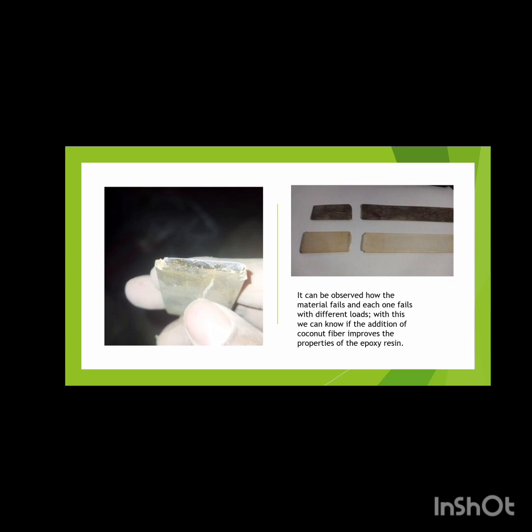After performing the tensile test, it was observed that both specimens showed a fragile behavior, and this is evident since in the data table they show very low deformation and a high tensile modulus of elasticity. Additionally, it was observed that by adding the coconut fiber to the resin, the load capacity increased, and therefore the ultimate tensile strength also increased in value.